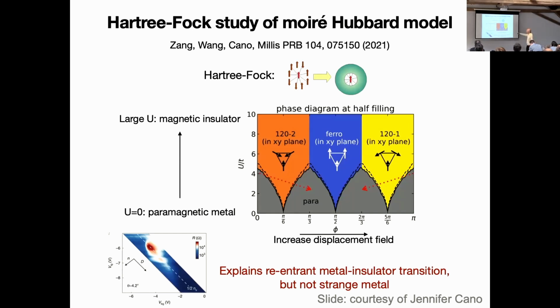And what you can do is tune with phi this magnetic transition down to a special value, phi equals pi over 6, where it now happens just at U equals 0. And this is because at phi equals pi over 6, the Fermi level lives on a Van Hove singularity. So the critical U is 0. And there is a rich zoo of magnetic phases here. There is a ferromagnetic phase and so on. This is just Hartree-Fock. Real life is actually even more interesting.